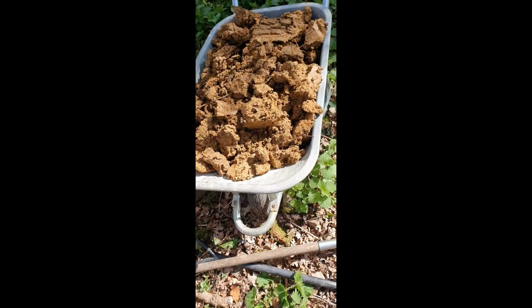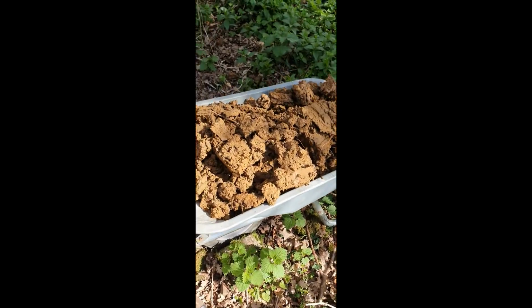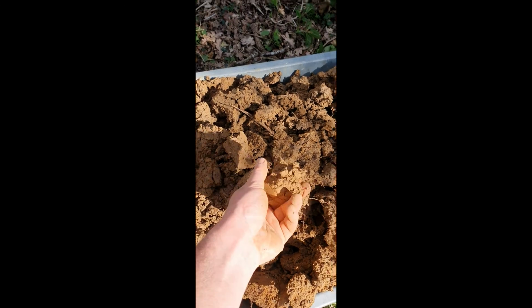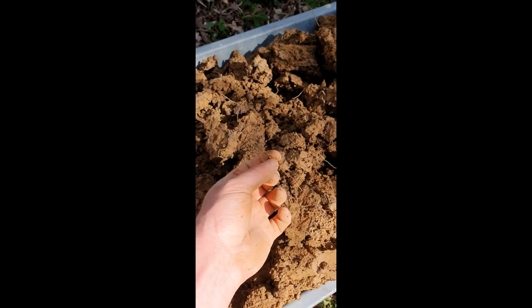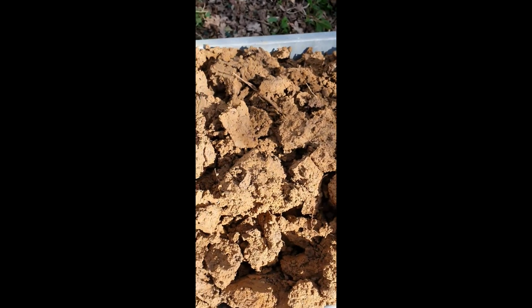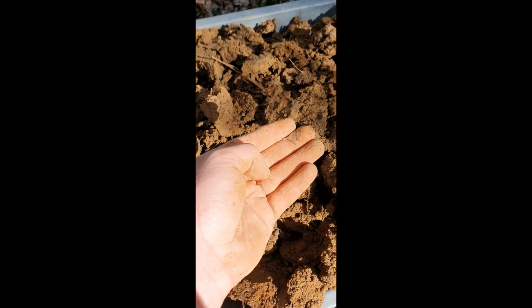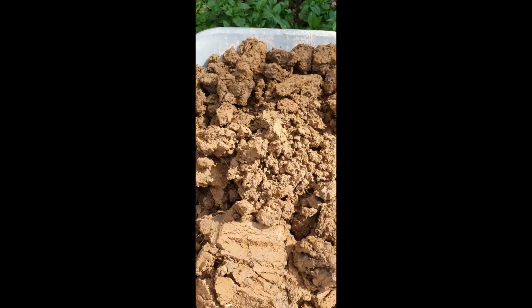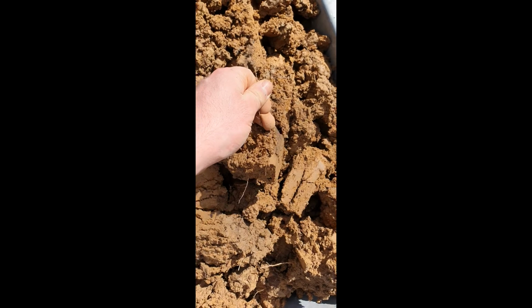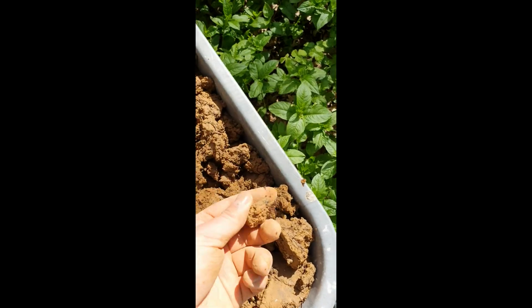That is an entire wheelbarrow's worth of nearly pure clay, broken up by hand, bit by bit, to make sure I go through it, trying to remove as much organic matter as I can, which is mostly roots, but also leaves. Pesky things break up very easily and attach to the clay. But the reason I'm trying to remove as much organic matter as possible is because in the firing process, obviously it burns away, and it causes shrinkage and cracking. Plus it can leave air pockets, which will cause it to expand and explode in the firing process. So it's about trying to purify the clay as best as possible by removing as much organic matter as I can, and that's why I've gone through it bit by bit, hand by hand, also removing stones.